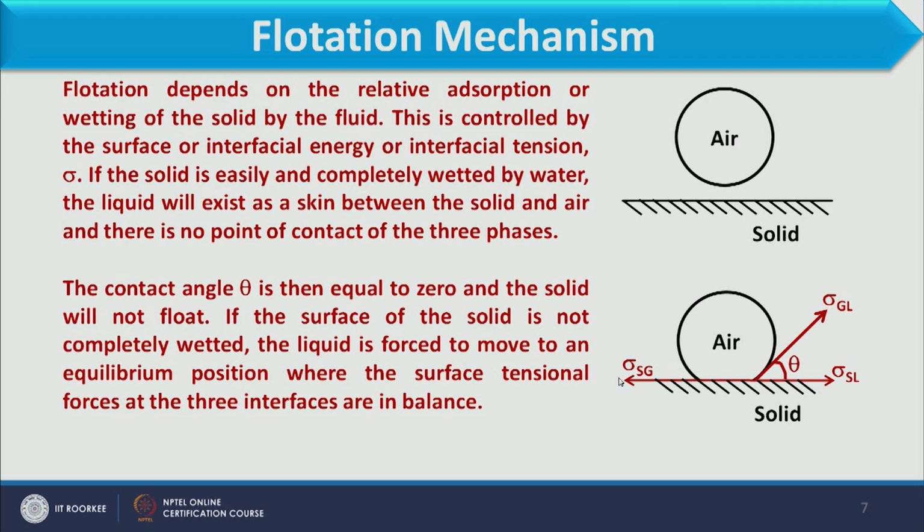To balance, the surface tension between solid and gas, sigma Sg, should be equal to sigma Sl plus sigma Gl cos theta.